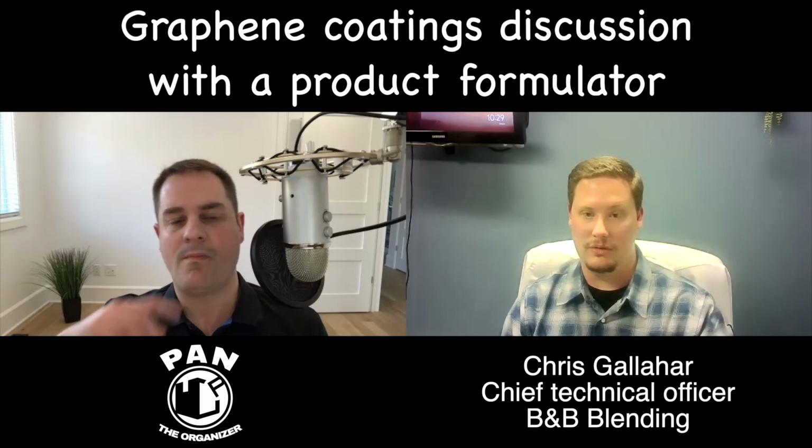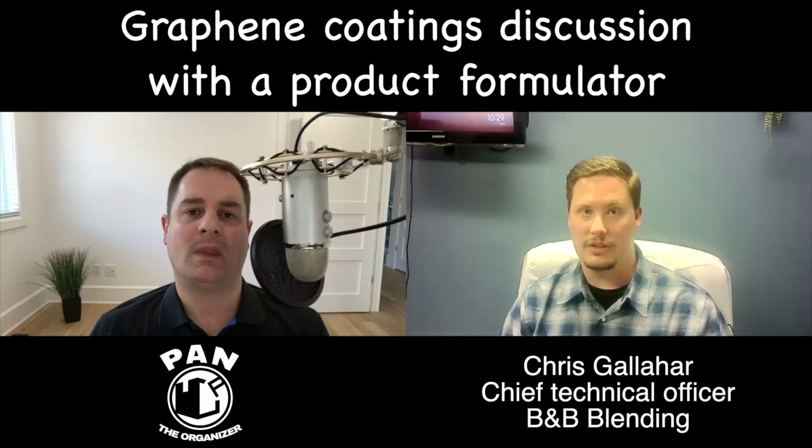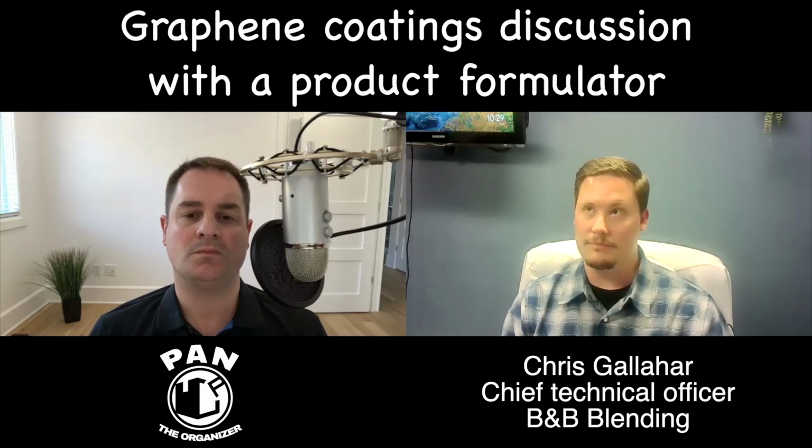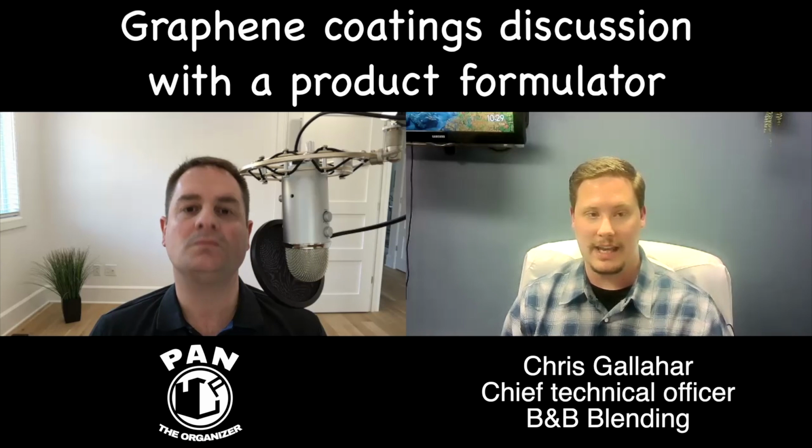But for the sake of applying to a vehicle, these are what we would refer to as ambient temperature curable refractory resins. You're using solvents to cut them so that you can deliver them to a vehicle. The solvents flash off. Oxygen's donated via water in the humidity in the air to catalyze the reaction, gives off ammonia, and makes a curable film that actually shrinks and cures into a glass-like state, right?